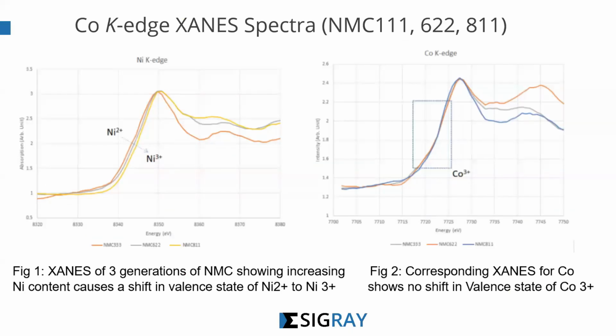And what if now we study the cobalt side, or the cobalt moiety of that NMC? You find that you don't have that shift in the cobalt because the cobalt oxidation state has not changed as you go from your NMC 111 to your 811.